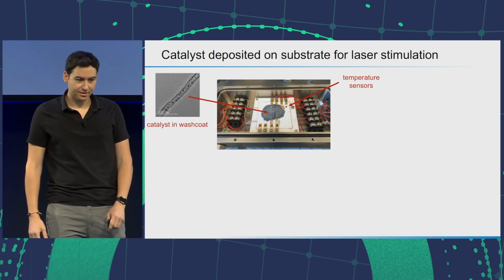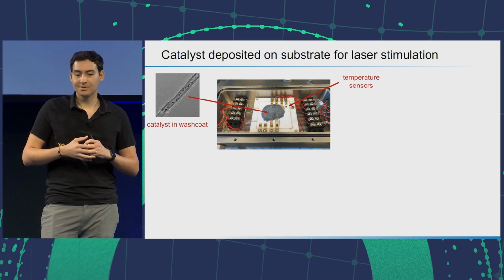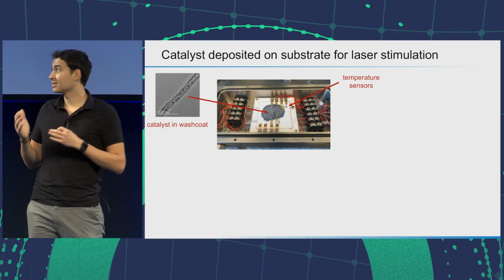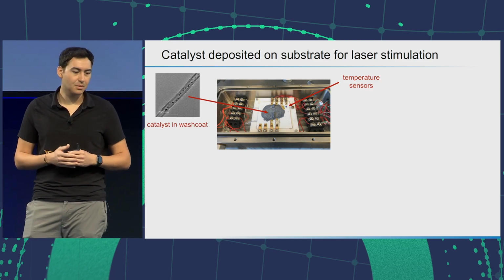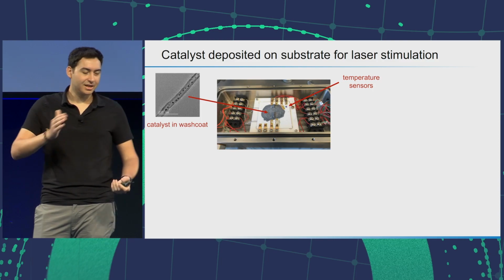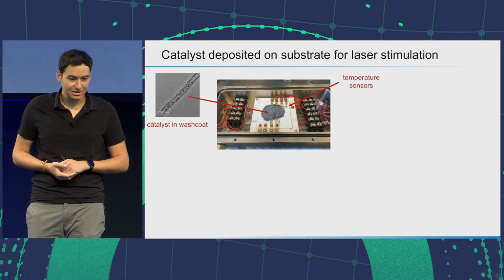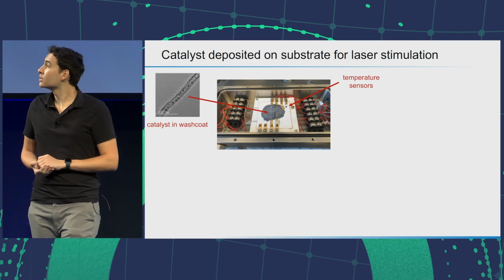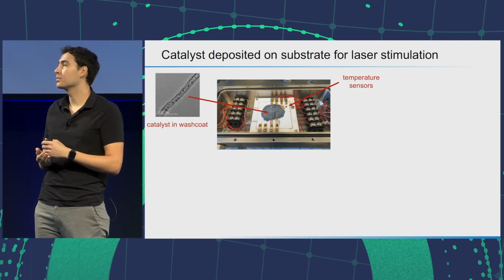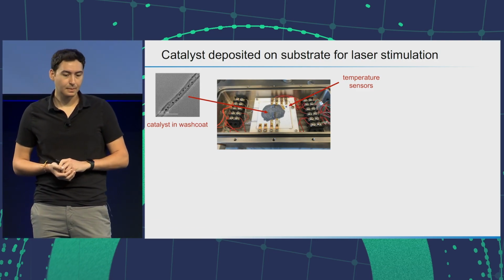So this is what our little reactor looks like. We start with our catalyst. The nanoparticles or carbon nanotubes are very powdery, so we had to come up with a recipe for a wash coat. It's like peanut butter. We put it on our sandwich bread there. That's a substrate, which has some temperature sensors, so we can record temperature data in real time with the RTDs.